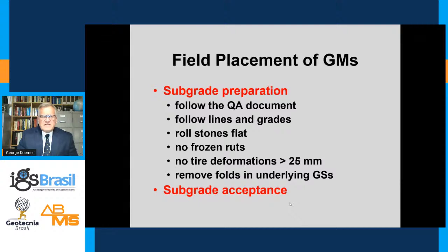You have to follow the QA documents, follow the lines and grades. It has to be stone free and flat. If you're in the winter time or near winter, in the late fall or early spring, you should have no frozen ruts. Tire deformation should be less than 25 millimeters. Nothing can be greater than 25 millimeters. Remove folds in any underlying geosynthetic, and then subsequently get a subgrade acceptance letter.